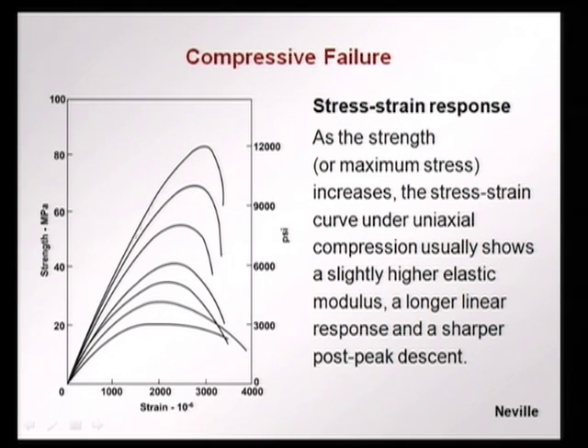We have a longer linear part for the higher strength concretes, because we have eliminated the defects, the interface is stronger, we do not have so much micro cracking before the peak load. The linear range is relatively more in a higher strength concrete than in a lower strength concrete. In the lower strength concrete you see more non-linearity occurring much ahead of the peak than in a higher strength concrete. So, you can utilize more of the linear part in a higher strength concrete. Obviously, the peak load is much higher because the strength is higher. You find that failure strains are almost similar, about 2000 microstrains is where failure occurs, and a little bit more in the case of higher strength concretes.